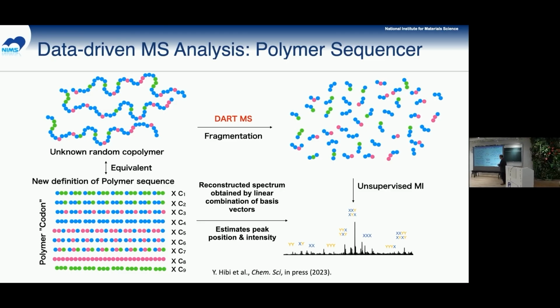Then we calculated the number of these segments, so that we can calculate how much of this segment is contained in the mass spectra. So we can tell that. Imagine this is sort of an alternating copolymer, a well-defined alternating polymer: blue, green, blue, green, something like that. If you know the length of these polymers, you can tell how much of these components is contained in the original random copolymers. That is our strategy.